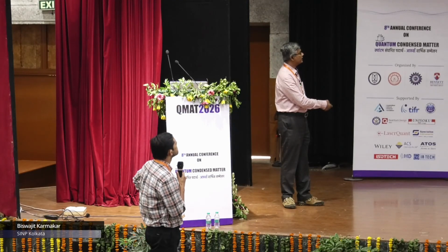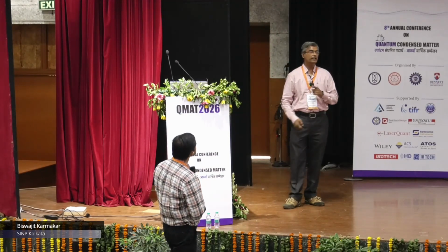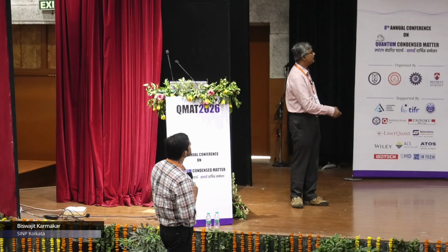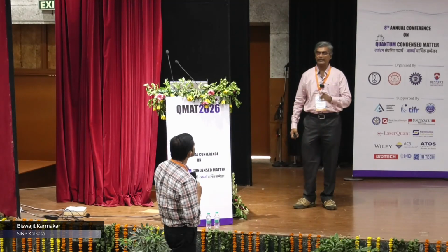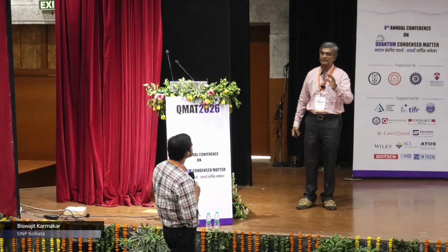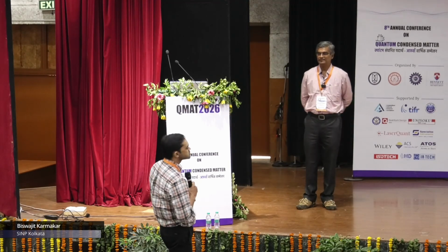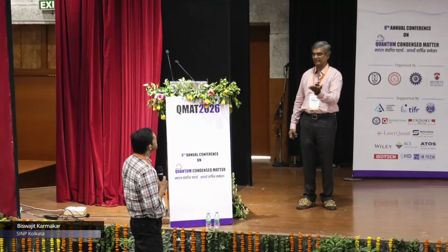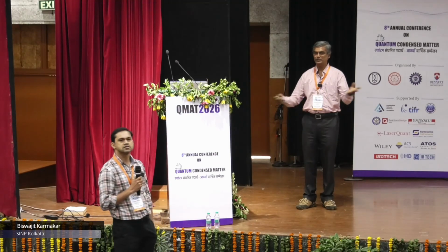If we decrease the thickness, then this factor will decrease. That's why if you work with graphene, the screening length will be low, so you can achieve this chiral metal phase even at 77 Kelvin. So at 77 K you could make some kind of chiral processor with graphene. It's a new concept.